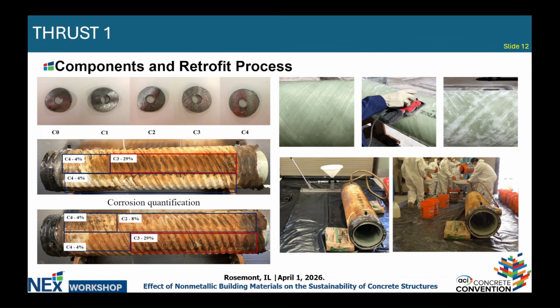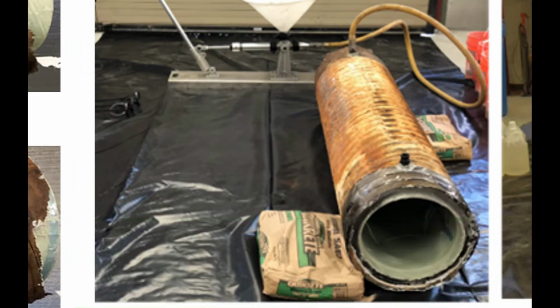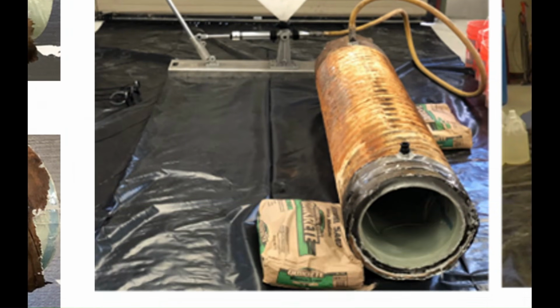The corrosion that was managed to be achieved was about 4% lowest and 29% maximum in the middle center areas. After surface preparation of these GFRP slip liners, the slip lining technique was conducted, where here you can see this corroded metal pipe with the slip liner system inside, and the grout filling is being carried on. So pumping of the grout is being carried on to make this sort of a composite system.